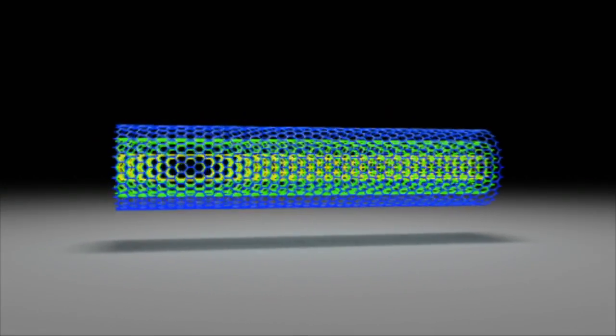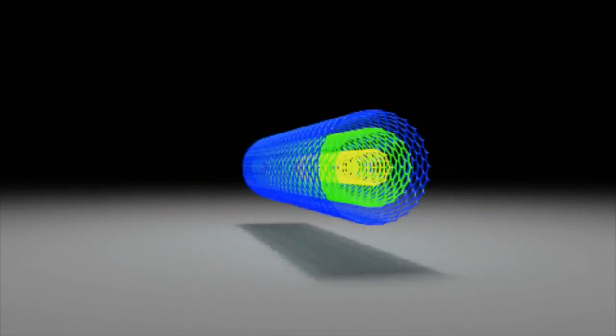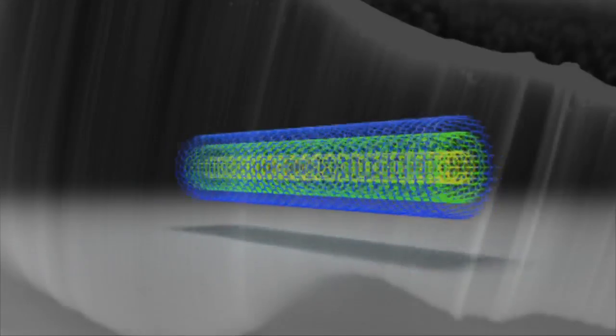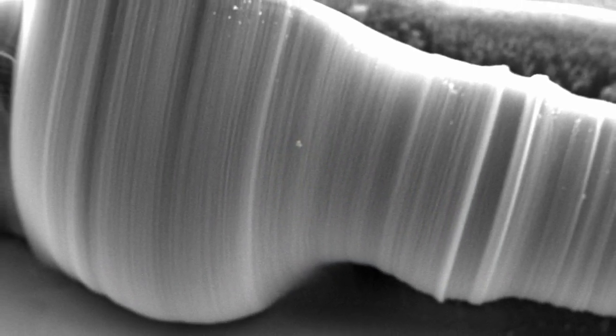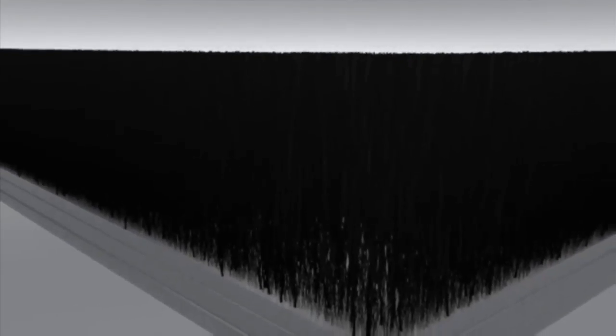The Goddard samples were grown multi-walled, so they're not just single-walled nanotubes. And they're also oriented straight up and down. The reason that the oriented samples are darker is because they're low density. Light can go in, it gets rattled around in there, and it gets absorbed.